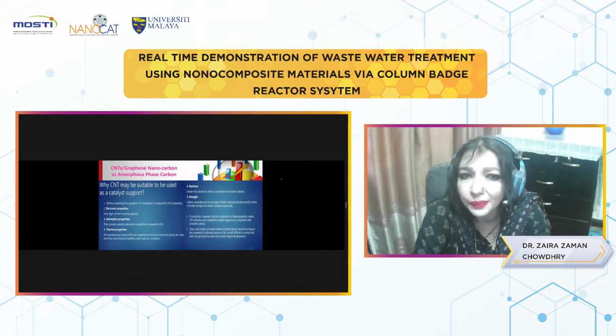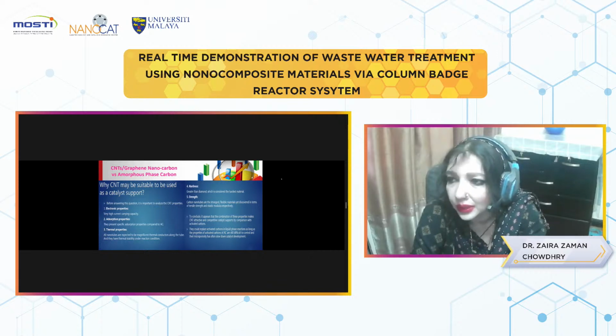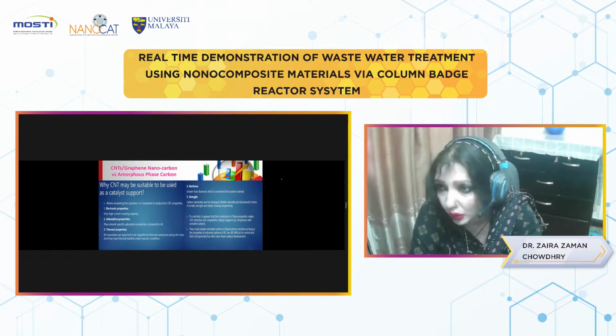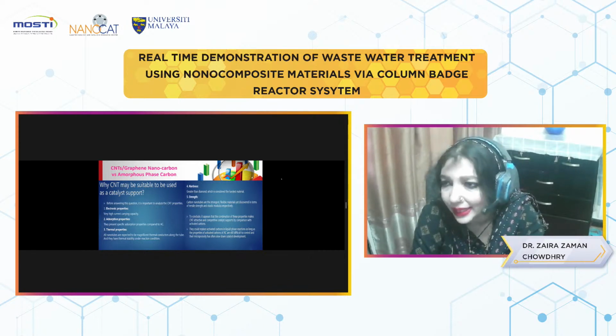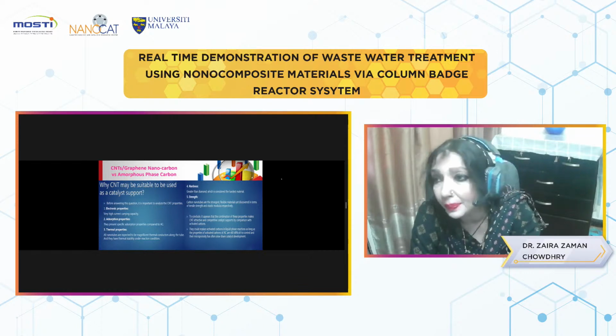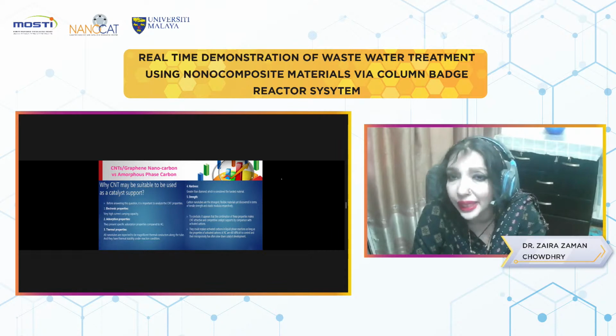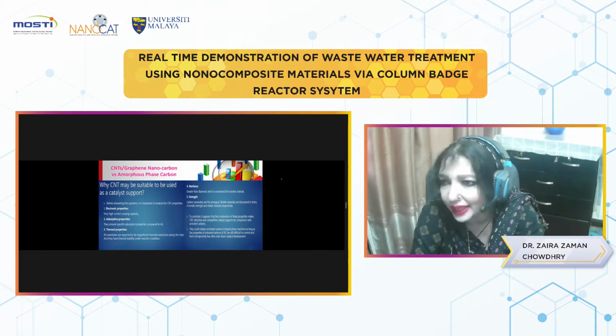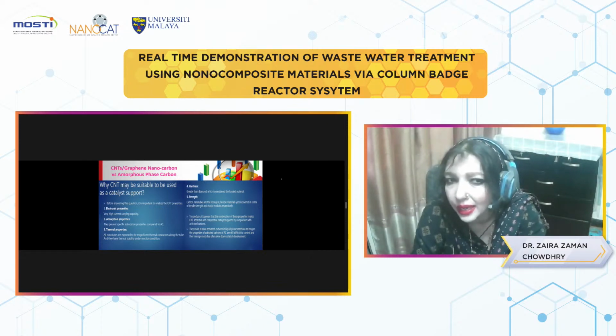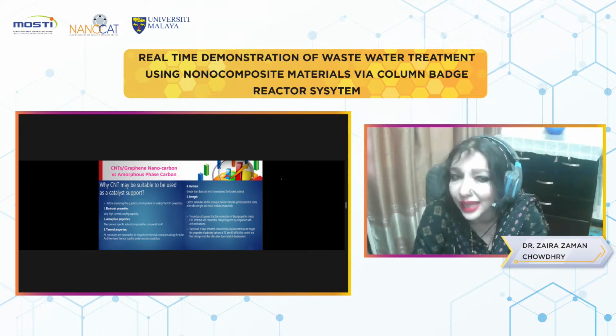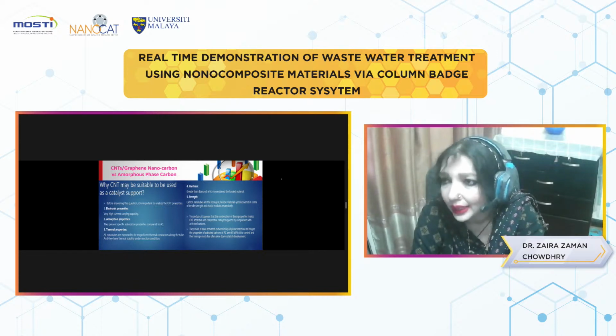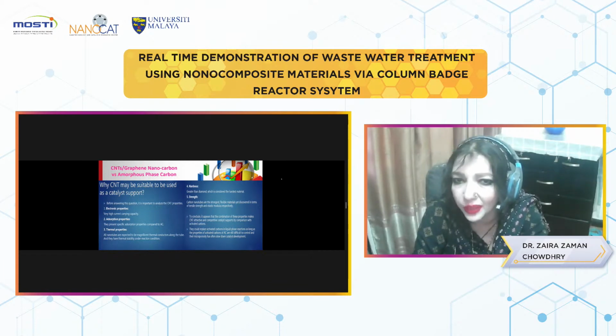Okay, why CNTs may be suitable to be used as catalyst support? Sometimes we go for water treatment catalytic wet air oxidation, where CNT is used as a catalyst and over it is some metal is doped. Let's say copper metal is doped or vanadium metal is doped, gold metal is doped, and then we pass oxygen in the water, which is called catalytic wet air oxidation. In this phase, the pollutant will be oxidized and there will be some simple fraction of molecule which will be adsorbed by CNT or it will be disintegrated. So water will be purified. Obviously, CNT is a good support because of its hardness, strength, electronic properties and adsorptive properties. Thermal properties also, it can withstand high temperature.